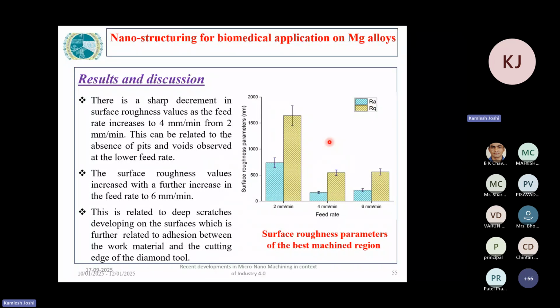The surface roughness was measured, and it was found that the highest surface roughness was with the lowest feed rate, and with an increase in feed rate the surface roughness improved. A sharp decrement in the surface roughness values is observed as the feed rate increases from 2 to 4 mm per minute, and this can be related to the absence of pits and voids observed at the lower feed rates. The surface roughness values increase again from 4 mm per minute to 6 mm per minute, and this is related to the deep scratches developed on the surfaces due to the adhesion between the workpiece material and the cutting tool.